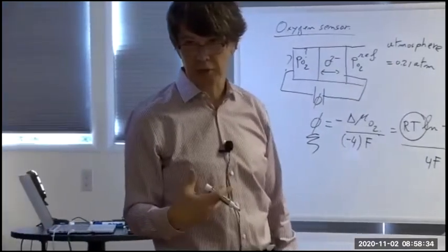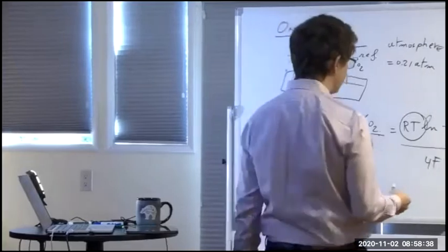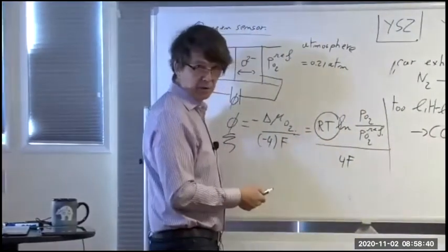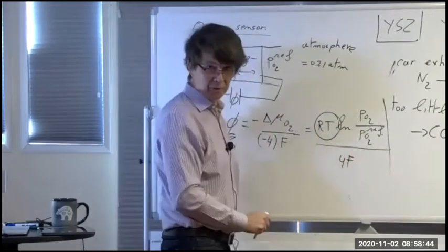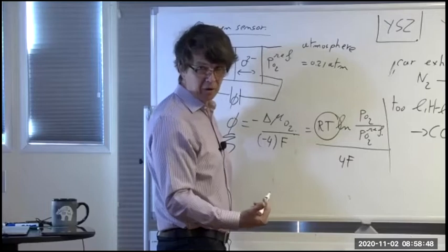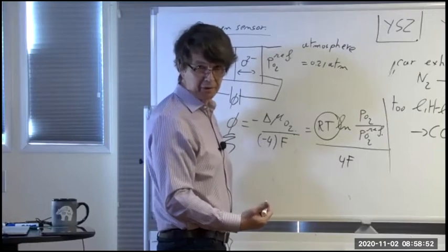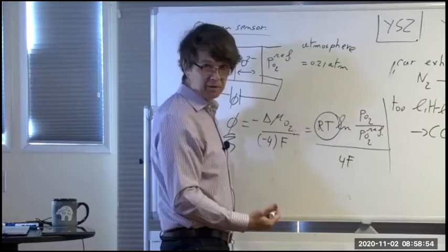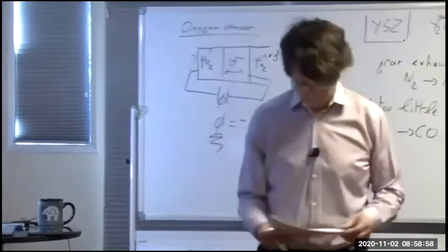It's very hard to know what T is because T is very inhomogeneous. So they also measure temperature in the exhaust, but in the beginning it's actually quite cold, and this relation is very confused because the temperature changes very rapidly. That's why your car is much more polluting when it's cold. It's in part because the engine is not very efficient, but the real part is that the oxygen sensor is very confused. It really doesn't know what to do.